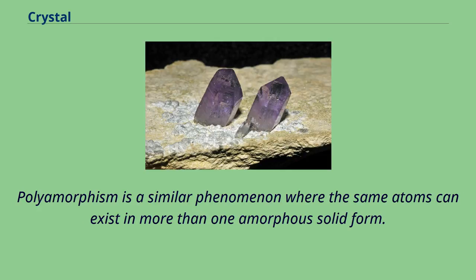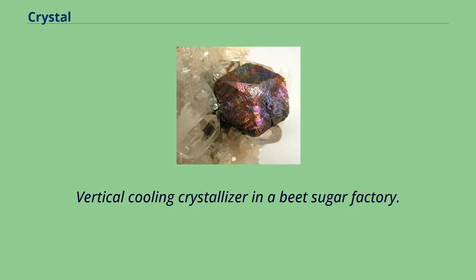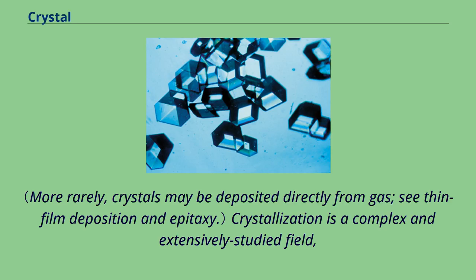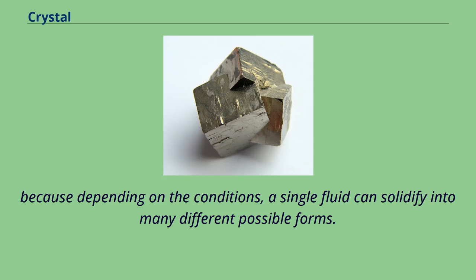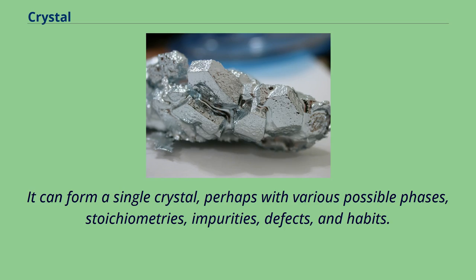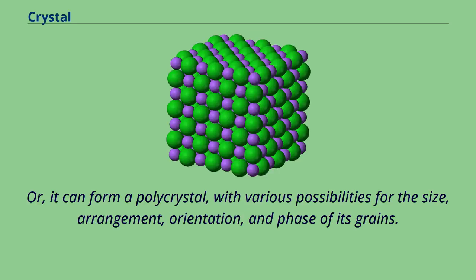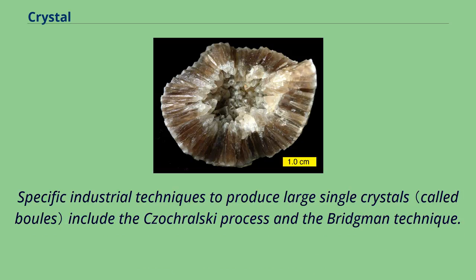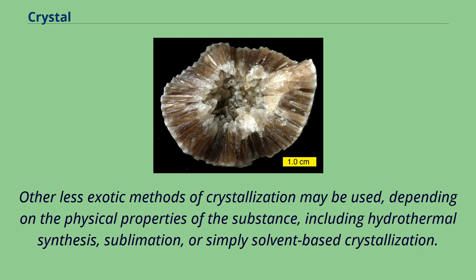Crystallization is the process of forming a crystalline structure from a fluid or from materials dissolved in a fluid. It is a complex and extensively studied field, because depending on the conditions, a single fluid can solidify into many different possible forms — a single crystal with various possible phases, stoichiometries, impurities, defects, and habits, or a polycrystal with various possibilities for size, arrangement, orientation, and phase of its grains. The final form of the solid is determined by the conditions under which the fluid is solidified, such as chemistry, ambient pressure, temperature, and the speed with which all these parameters are changing. Specific industrial techniques to produce large single crystals include the Czochralski process and the Bridgman technique. Other methods include hydrothermal synthesis, sublimation, or solvent-based crystallization.